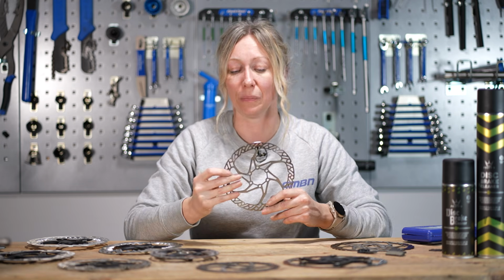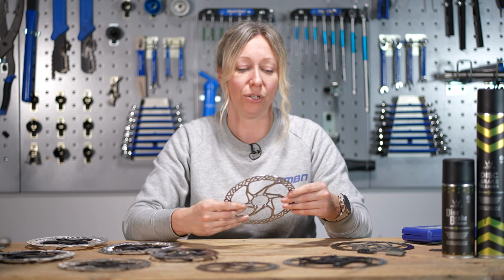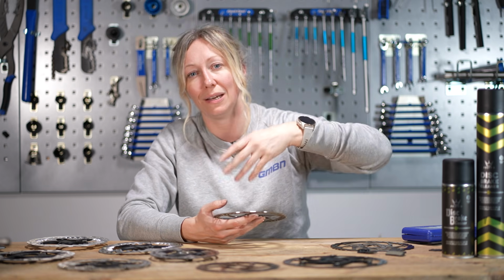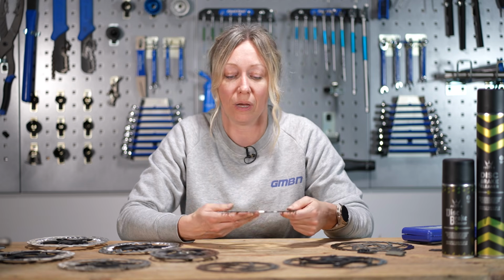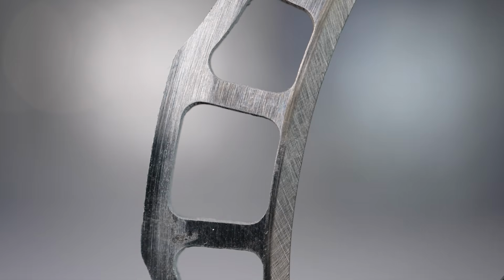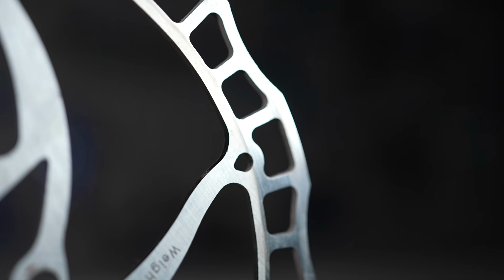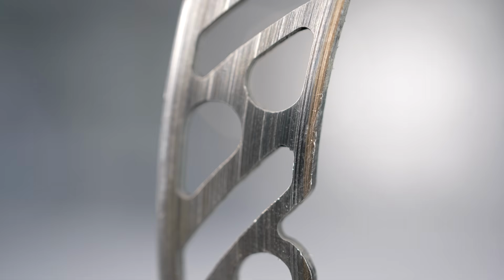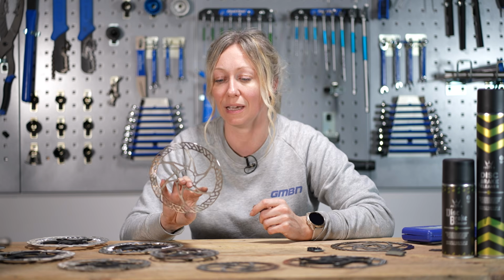And then, of course, there's contamination. Something I've been doing for this entire time of this video is touching disc pads, or getting lubricant on your disc pads, or cleaning your bike, not covering your discs, and accidentally spraying chain gunk all over your discs. That will contaminate the disc and it just won't work so well. And if you consider, as we've talked about, that discs have tiny pores with bits of resin or sintered pad material in there, once you've contaminated that, I mean, you can resurface it, but it's very unlikely you're gonna get rid of it. So it might be time to consider replacing them if you have contaminated your discs.